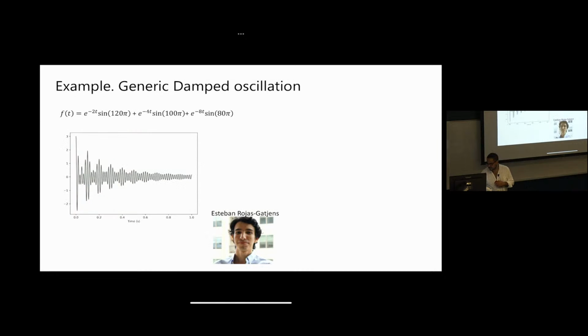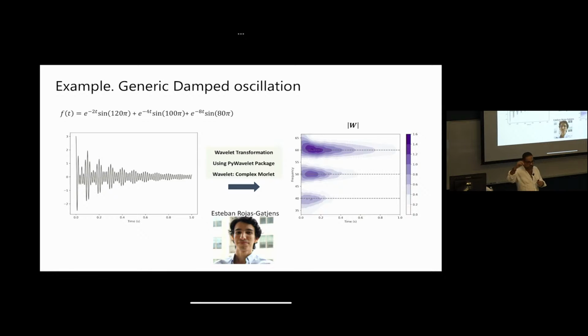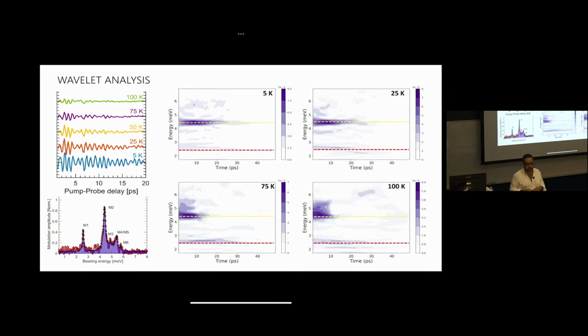This is where Esteban comes in, and he does not do a Fourier transform of our oscillatory response, but rather a wavelet transform. And if you want to really know the details, you have the expert here rather than me. But what you show is that if you take this data that we used to measure the resonant impulsive stimulated Raman spectrum, but you don't do a Fourier transform, you do a wavelet transform, you get not just the intensity spectrum, but the time dependence. And so what you notice is that there's a phonon here. This is M2, the one that non-adiabatically mixes, the most important one in protecting excitons against scattering, carriers against scattering as well, that is highly temperature dependent.